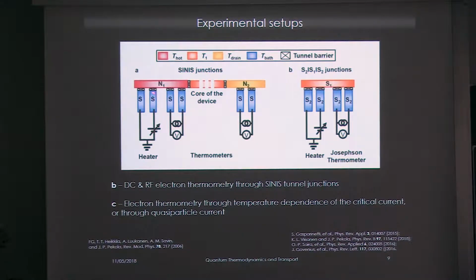Thermometry and heating, in order to heat one part of the circuit with respect to the other, are done thanks to coupling our regions of interest. Here we have the core of the device. The core of the device is the one which is sensitive to the phase, to the flux. And the other parts are the reservoirs, the source and drain, where we impose, for instance, a chosen temperature. So we create a thermal flux flowing into the system, and then on the other side we measure the other temperature. And how do we do this? We tunnel-couple typically superconducting tunnel junctions, NIS junctions, that act as a heater or as a thermometer.